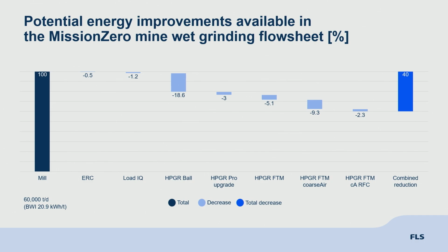So changing out a SAG mill on a very hard Bond work index, by the way, this is a very hard composite low-grade ore, then you can get 18%. And then if we did our HPGR Pro upgrade, you could get a further 3%. And then if you changed out the ball mill for an FTM, you could get a further 5%.